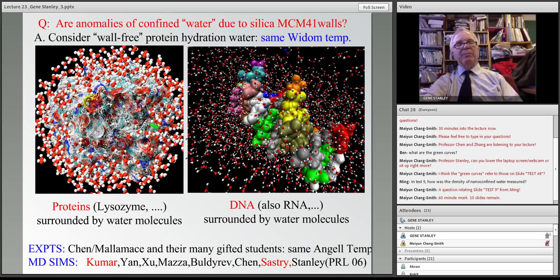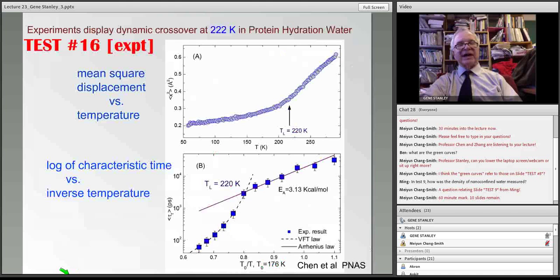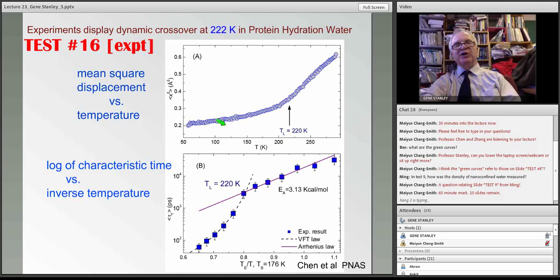And moreover, the temperature at which these anomalies occur is exactly the same. Here is, for example, one of the classic experiments where one measures the mean square displacement as a function of temperature. At very low temperature it has a solid-like form with a very low slope, and then suddenly around the magic temperature of 225, there's an abrupt change of slope and a much bigger slope, if you will, corresponding to a rigid or strong LDL fluid crossing over to a less rigid HDL fluid. And similarly here, this is the characteristic time which is measured, and the same thing happens, a crossover at around 225.